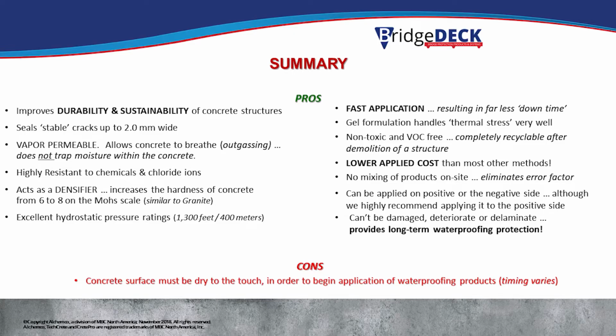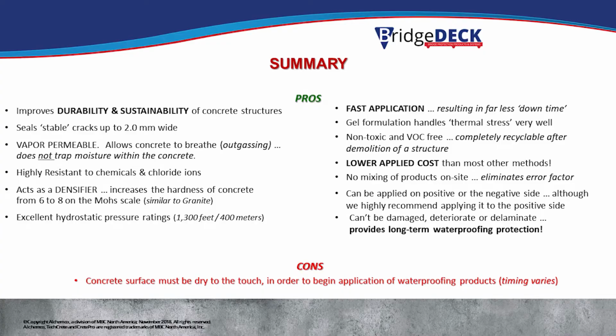It's a high resistance to chemicals and chloride ions. It increases the hardness of the concrete from 6 to 8 on the Mohs scale, so it's going to densify the concrete as well. It's going to increase the compressive strength. The test that we have is about 40%, so from 3,500 psi to 5,000 psi. And as I mentioned of this product being a waterproofing product, we have a water pressure test of 1,300 feet of water pressure with no damage to the waterproofing and no leaking, which is really unheard of. I don't know any other technology that's able to handle such a strong hydrostatic pressure.